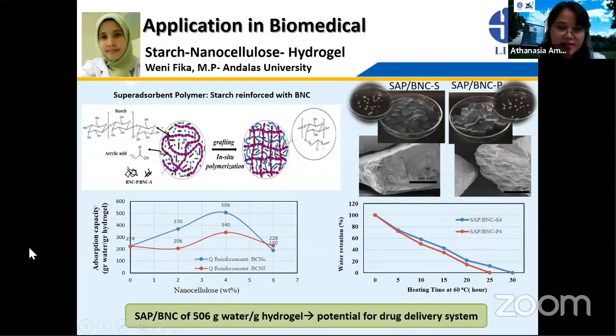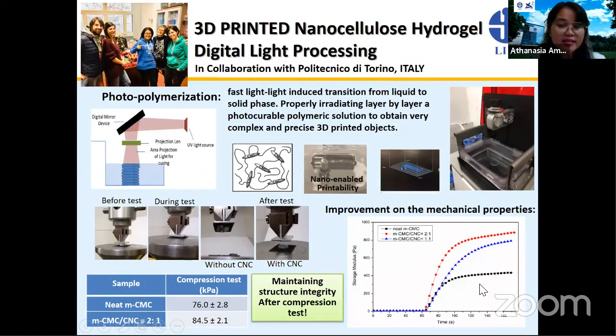So this system also helps with water retention, and can retain water for up to 30 hours in an environment at about 60 degrees Celsius. The third method to develop the production of hydrogels is quite a novel advanced technology, using 3D printing, especially digital light processing.